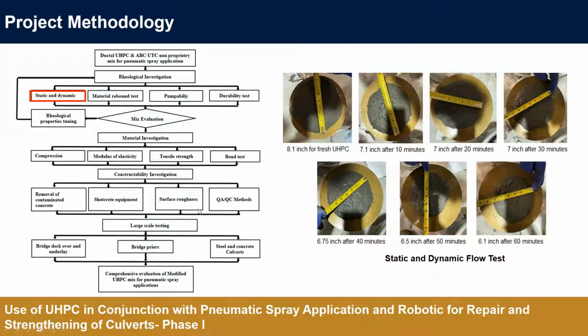So if I start with the static and dynamic flow test, here we are using time intervals to measure the change in the flow of the UHPC material over time. You can see here how much the static flow changes over time. Every interval of 10 minutes, we are monitoring the open time of the material.